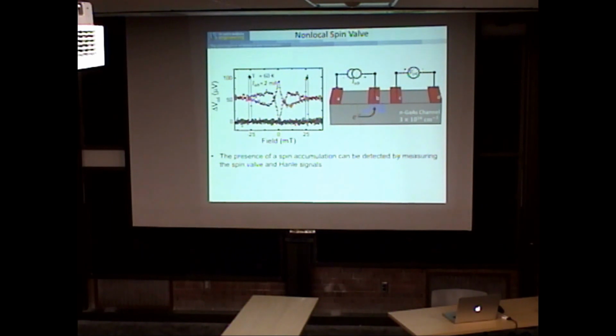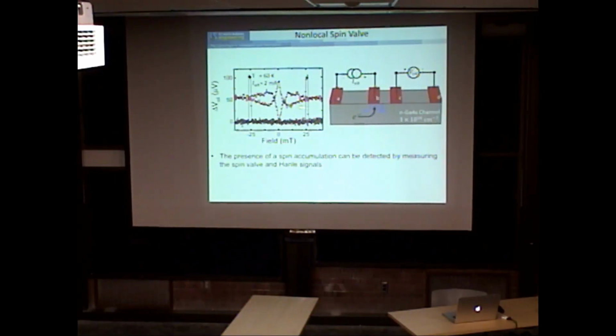Spin polarization. So here, as an example, this is the delta V that we measure between C and D. This is when they are anti-parallel, and then parallel, anti-parallel, and parallel when you sweep the magnetic field. And this is the Hanle measurement with the perpendicular field, showing that the Hanle signal follows exactly the same behavior that we get for the spin valve measurement.